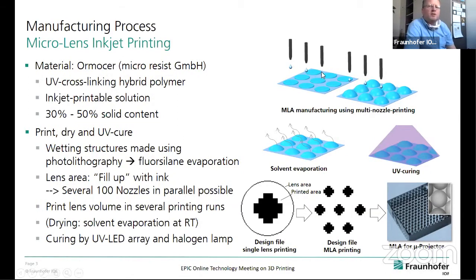We have a pre-patterned substrate. That is something very interesting. This is what the EPIC community can do for us. We still need pre-patterned surfaces. We have been in contact with Heidelberg, for instance, about that. And we print our optical material onto these pre-patterned surfaces, and simply by surface tension, the material forms a microlens. And by specifically formulating our optical material, we are even able to get rid of this solvent evaporation process. So we only have to do the UV curing of the printed material to create then the real microlens array.